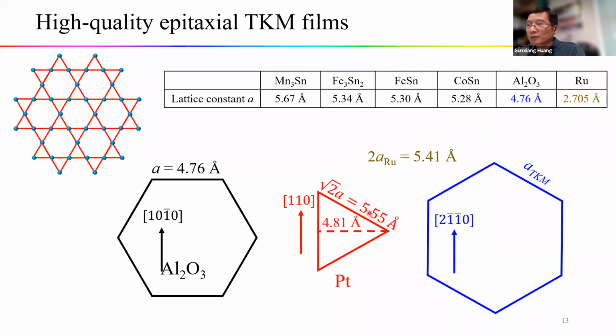the lattice mismatch between the platinum and the ruthenium is also about a 2% range. So we could also grow ruthenium on top of platinum, and its lattice constant is also within about a 2% difference with the lattice constants of these three materials. So in other words, we may be able to grow epitaxial these TKM films by using the platinum or ruthenium buffer layer on this sapphire substrate.